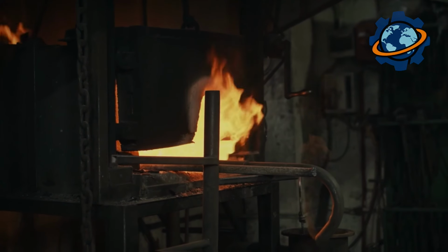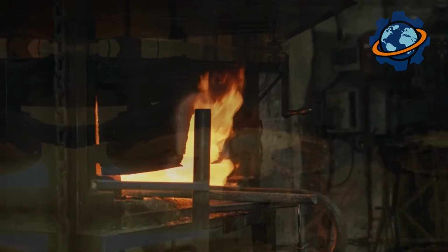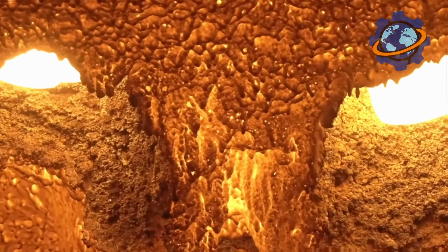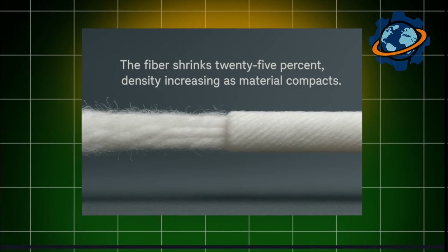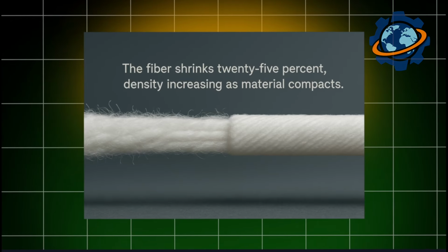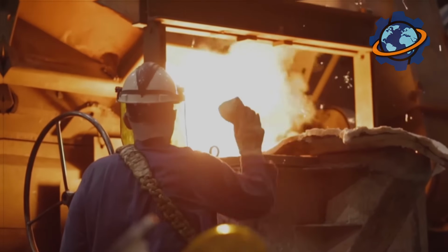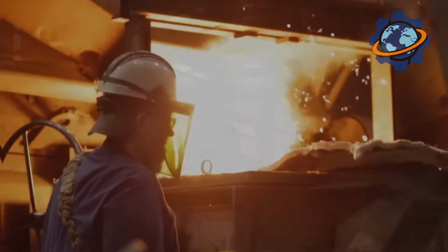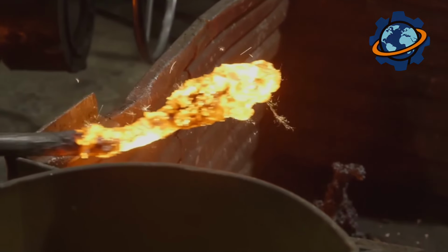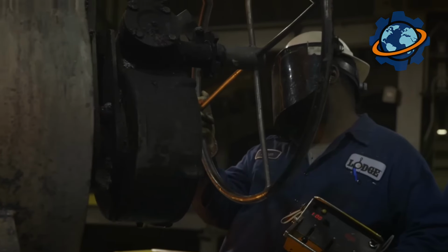The process occurs in stages. First, furnaces heat fibers to 2,700 degrees, driving off 90% of non-carbon atoms. The fiber shrinks 25%, density increasing as material compacts. Second stage furnaces push temperatures to 4,000 degrees for graphitization, the process aligning carbon atoms into perfect hexagonal sheets stacked like microscopic playing cards. This crystalline perfection gives carbon fiber its extraordinary properties. Processing takes 3 hours, crawling through furnace sections totaling 1,000 feet long.